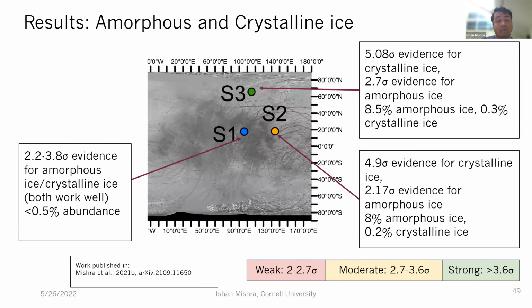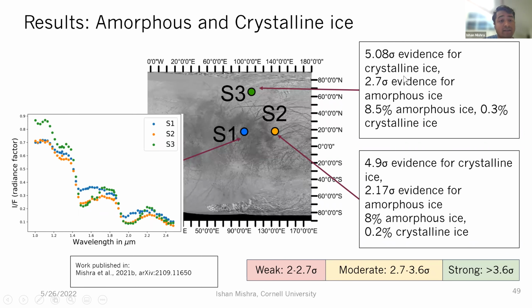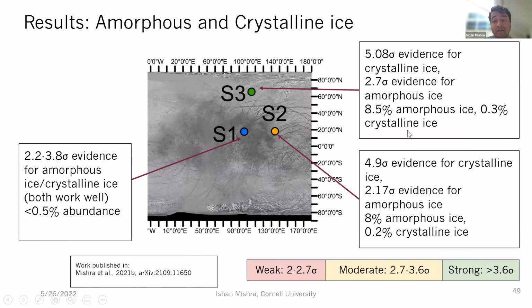As for water ice, in S1, we found that there was weak evidence for water ice, and both of them kind of work. So the abundance was just too low to tell them apart. Whereas in S2 and S3, we found very strong evidence of crystalline ice. And that is because crystalline ice has this strong 1.65 micron feature that you can clearly see in the S2 and S3 data, and it's missing from S1. So that's why we're expecting it to come out at a high significance.